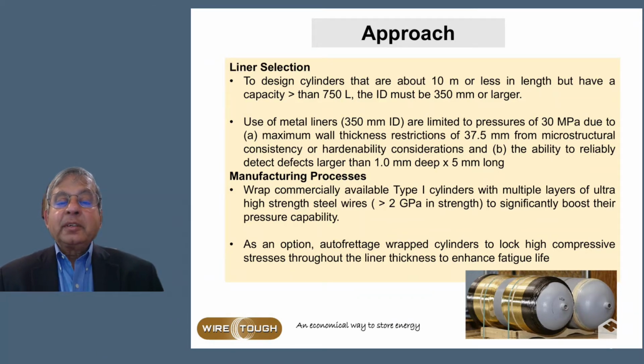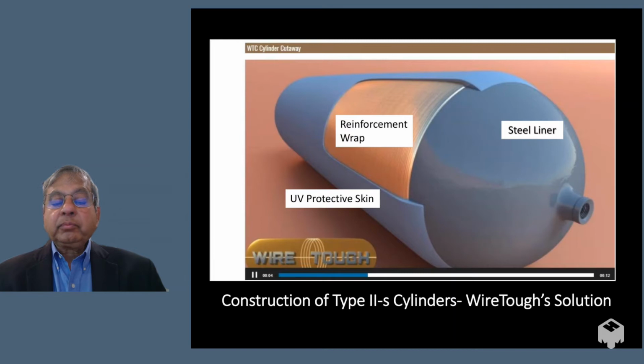The manufacturing processes consist of wrapping commercially available Type 1 cylinders with multiple layers of ultra-high strength steel wires with strength levels that are greater than 2 GPa to significantly boost their pressure capability. As an option, autofrettage wrapped cylinders to lock high compressive stresses throughout the liner thickness to enhance fatigue life. The schematic of our design is as follows in this figure. You have the steel liner. The steel liner is reinforced with the steel wire wraps, and then you have a UV protective skin on top of that, and that essentially makes a complete cylinder system.